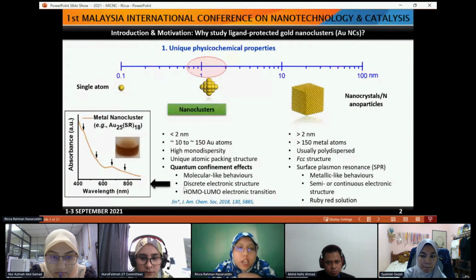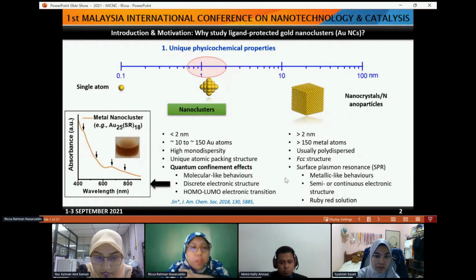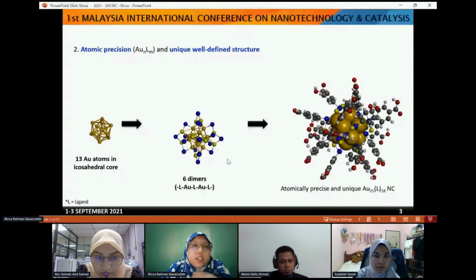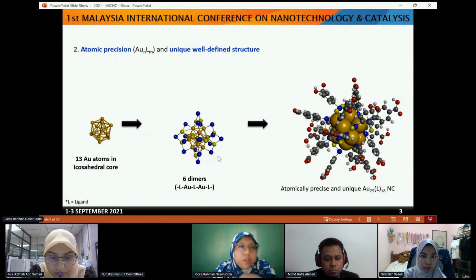So it also has a HOMO-LUMO electronic transition, as compared to nanoparticles, which have a semi-continuous electronic structure. If you look, the color is also different. The color is brown, bright brown. However, if you go for gold nanoparticle, the color is ruby red. So this is another unique thing about this ligand-protected gold nanocluster, which you can produce with atomic precision.